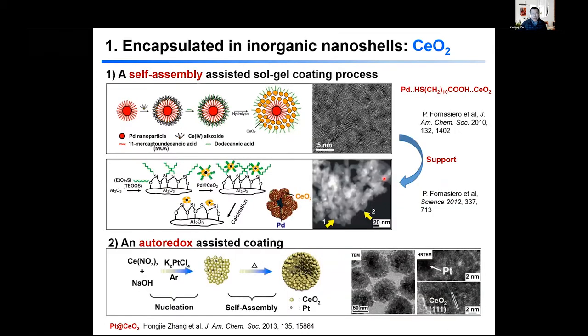Another type of oxide is cerium oxide, which is widely used as a support for catalysis. In this case, people use different ways to encapsulate nanoparticles inside. And here I just show you two typical ways. One is based on this self-assembly assisted sol-gel coating process. For example, in this case, people start with palladium coated with the ligand MUA.